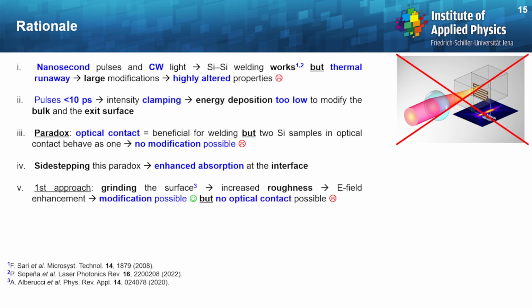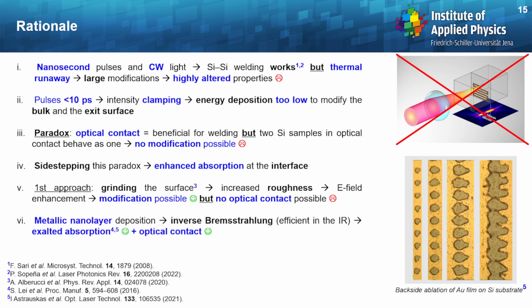A first approach would consist of grinding the surface, meaning that the roughness of the samples would be increased. Then there will be an enhancement of the electric field, and modifications would be possible, yes. However, the optical contact cannot be achieved between two raw samples.